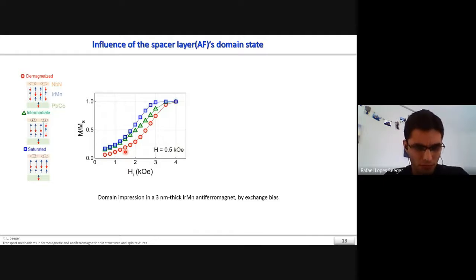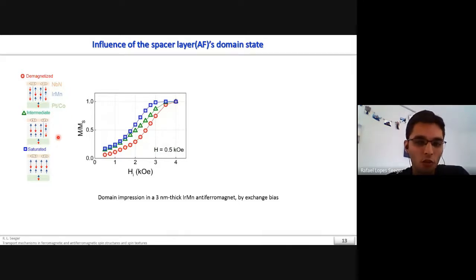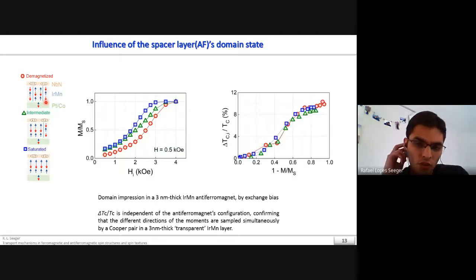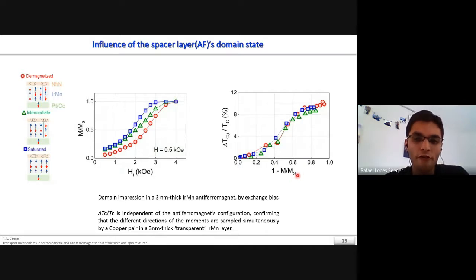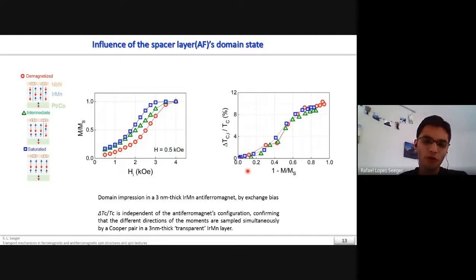We then considered whether the domain state in the antiferromagnetic IrMn layer influences superconductivity. We used a domain replication approach to stabilize several states in the IrMn layer at low temperature, and then obtained hysteresis loops where the shift along the field axis depends on the magnetic state of the IrMn layer. The results show that the recovery in critical temperature as a function of the magnetic configuration of the PtCo ferromagnet is independent of the magnetic state of the anti-ferromagnet, meaning the AFM state does not matter for Cooper pair transport.